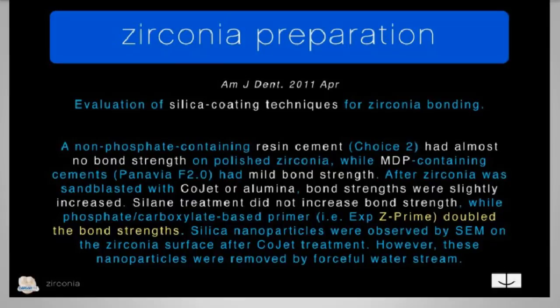Here's another one basically saying that the resin cements to zirconia didn't bond. You couldn't bond just the resin to it without a primer. If it had MDP, like Panavia, within the cement, it was better. But if you put on something like Z Prime, a specific primer for zirconia, it doubled the bond strength. People say, well, can I put a CoJet on there? Well, you can, and it works a little bit. It's highly debated whether or not the CoJet works, because you're trying to put silica onto the zirconia.